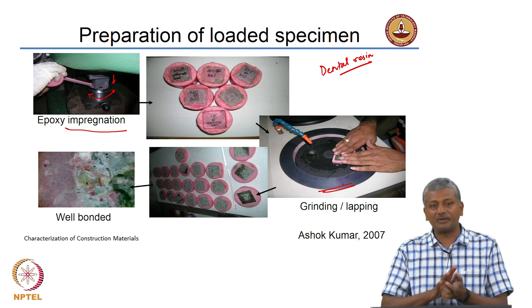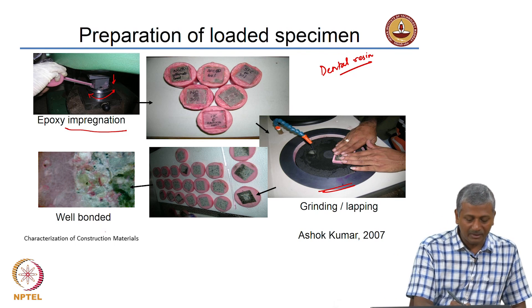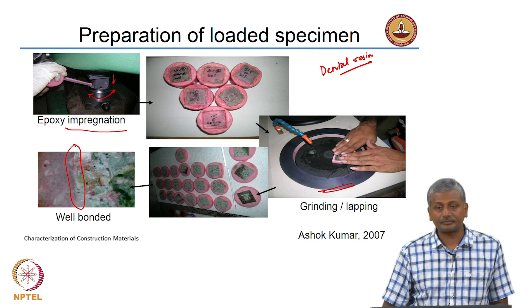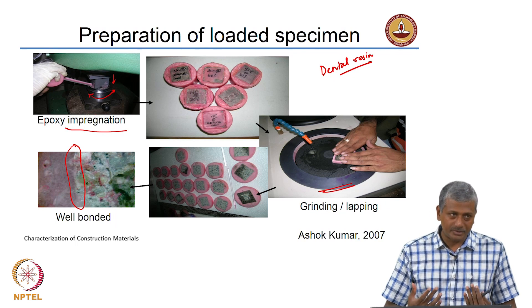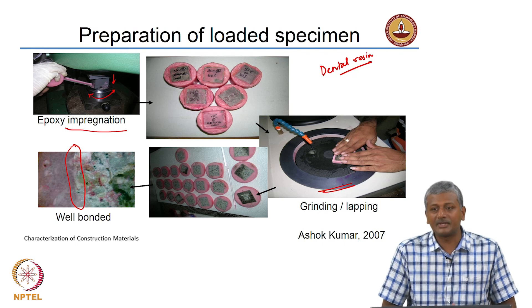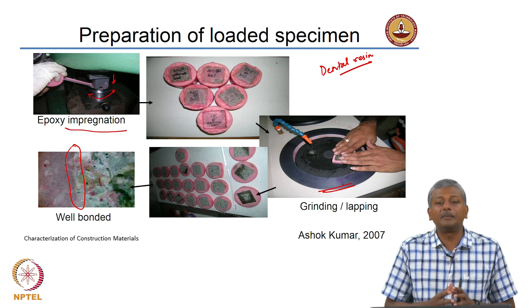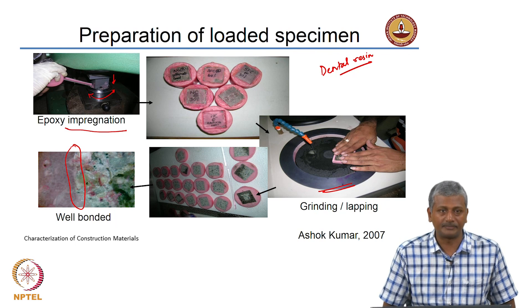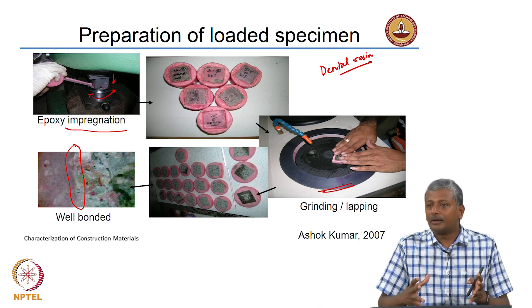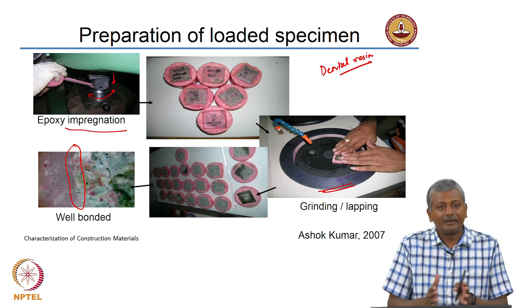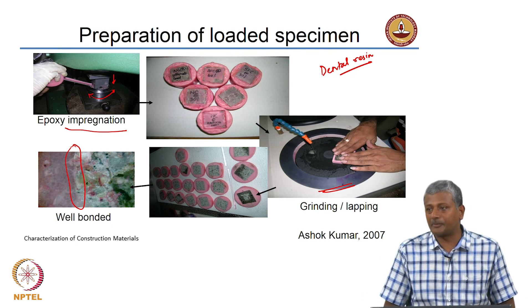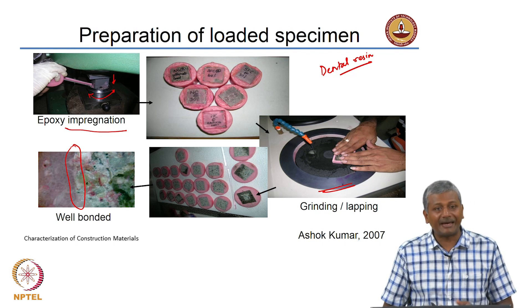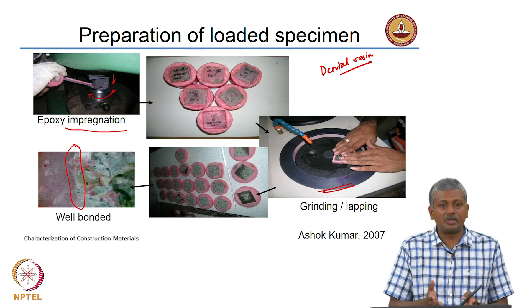We did grinding and lapping to obtain a degree of polish, and under the optical microscope the bonding between the epoxy and the concrete appeared quite good, with no visible gap. Whether the original cracked structure was preserved is debatable, but at least full unloading was prevented while the epoxy encapsulation was in place. Because the epoxy hardens while the load is still on, you do not expect significant unloading to occur.